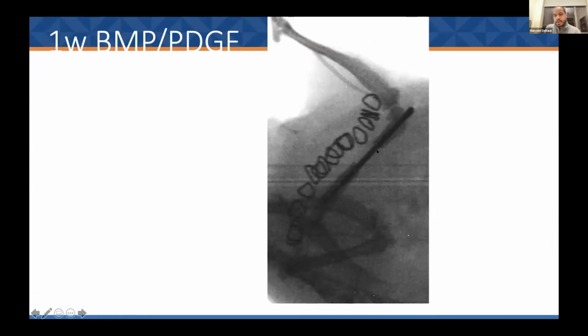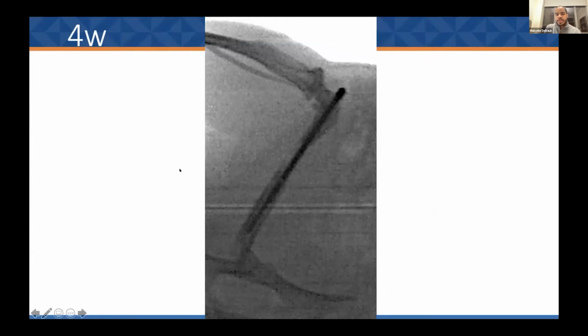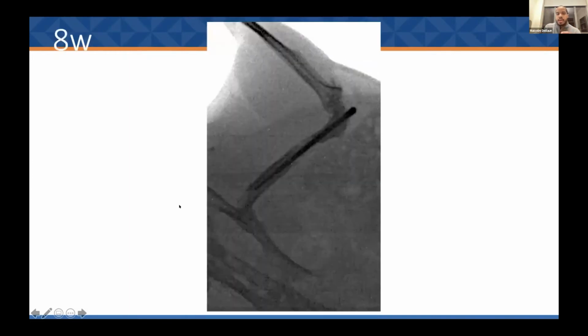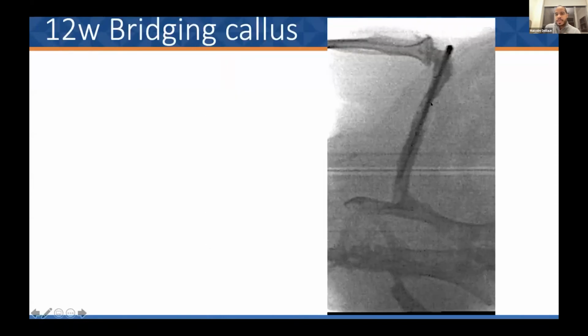You guys can see there's a very large defect here in the femur that wouldn't heal on its own. But what you don't see is that there is a scaffold that has two types of growth factor incorporated on the membrane that is in this space. But then over time, the healing process starts, and at 4 weeks, you start to see a little bit more calcification, a little bit more bone growth. You see the bone ends are trying to find their home there. At 8 weeks, it looks a little better, but not quite there yet. Still dependent upon that rod and dependent upon that implant. But then at 12 weeks, you see nice bridging callus all the way from end to end, and that's considered a healed fracture.